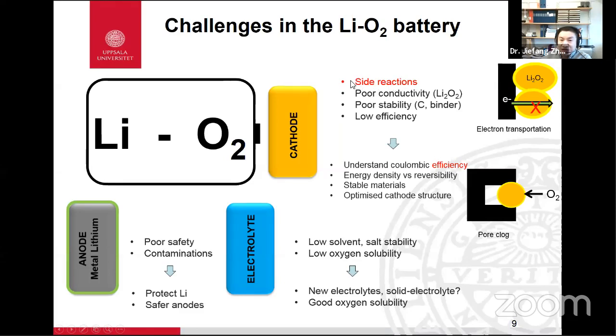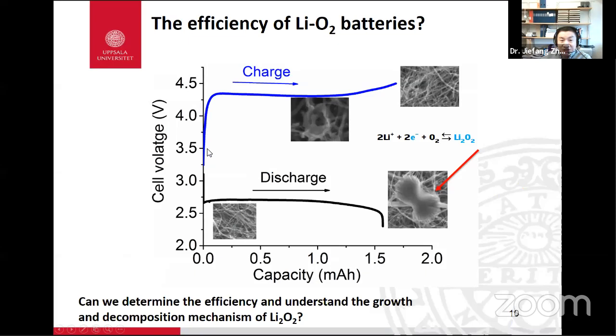Because there are a lot of side reactions. So the problem is how we know that the battery is running the ideal electrochemical reactions, not the side reactions, and how to define the efficiency, because the definition used in the lithium ion battery doesn't work for the lithium oxygen battery. If you only judge by the electrochemical profile, you don't know whether the capacity is from the ideal electrochemical reaction or side reactions. That's why the definition of the efficiency is also a problematic issue.